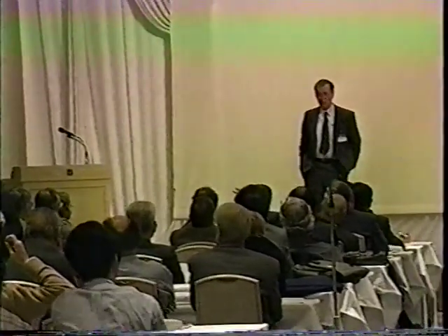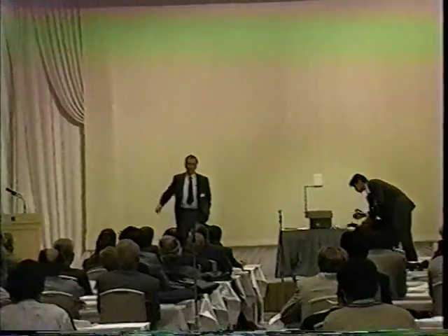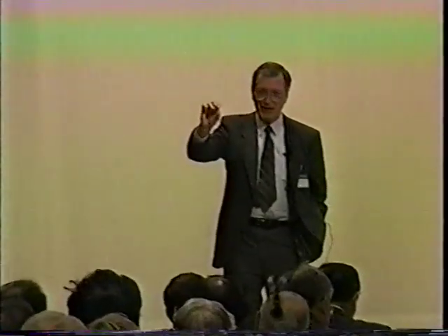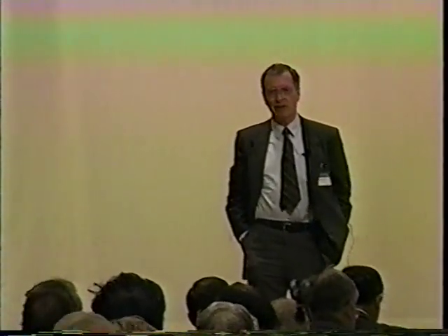In the nickel one, which we've been looking at, there are 1,000 beads, and we've run 4 different independent neutron activation analyses on 10 beads taken from the top, 10 from the next layer down, 10 from the next layer, and 10 more. So we've sampled something like 40 beads out of 1,000. Because we've done it in layers, we feel that it's fairly representative.